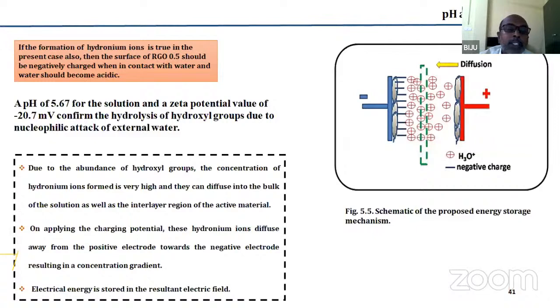Now, these hydroxyl groups are abundant due to the very high concentration of OH groups in our RGO material. And in fact, these hydronium ions can intercalate within the RGO layers to store energy. Now, if this mechanism that we propose is true, then we thought that if we create a temperature gradient between two similar electrodes, these ions should migrate to the colder junction, which should self-charge this supercapacitor. So if our hypothesis of the energy storage mechanism at the RGO-water interface is true, then we should be able to thermally self-charge this supercapacitor.